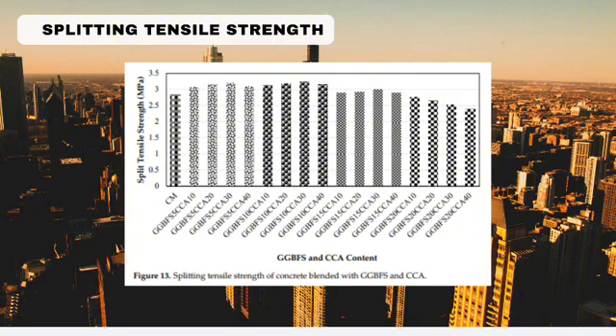The outcome is that the splitting tensile strength is boosted by the accumulation of GGBFS up to 10% as a replacement for PC and CCA up to 30% as a replacement for fine aggregate, and after further accumulation of CCA the strength plummets at 28 days. The increase in split tensile strength is associated with the CCA and GGBFS, which possess more specific surface area than the PC, developing the concrete interfacial transition zone.